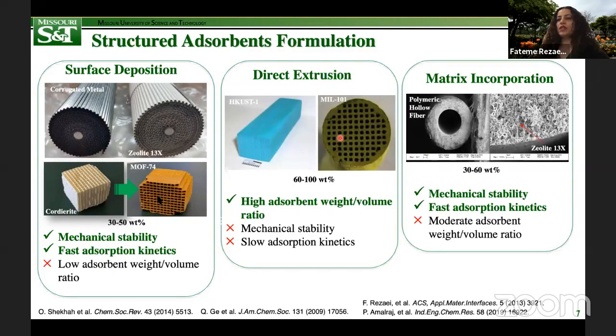Now, the third approach that I'm showing you here is matrix incorporation, by which adsorbent particles are embedded within a mesoporous or sometimes macroporous matrix, which is typically a polymeric material. In the past, various zeolites and aminosilicates have been incorporated into polymeric hollow fibers, with some examples shown here. The mechanical stability is high. We get fast adsorption kinetics, and also this approach allows for tuning material properties.